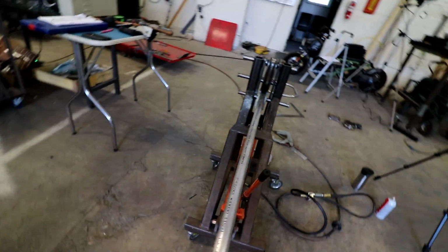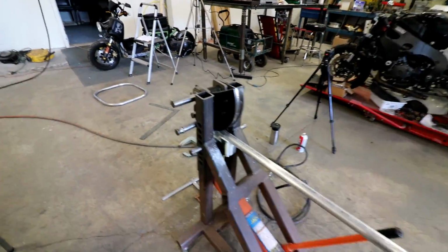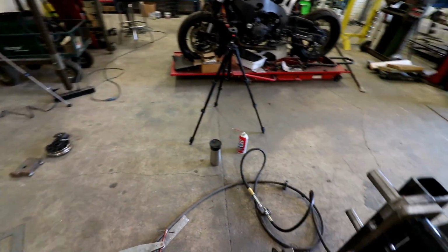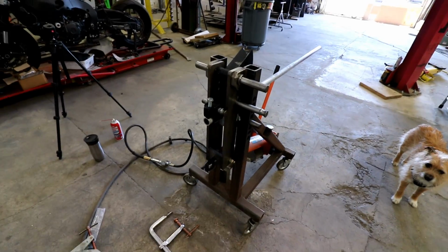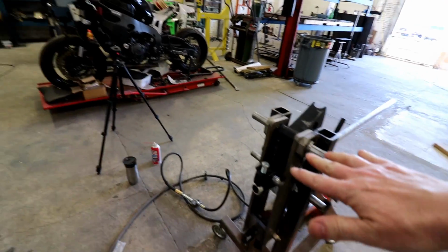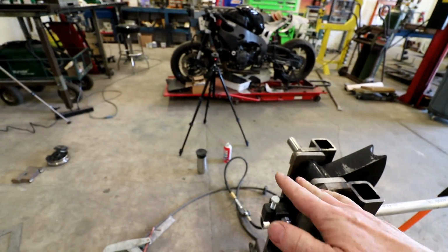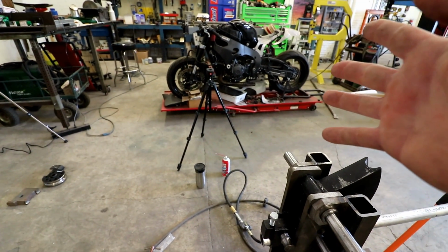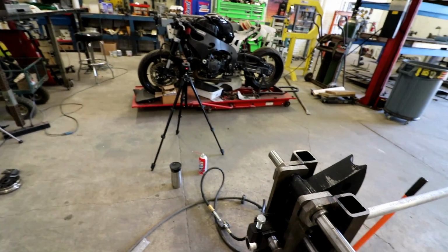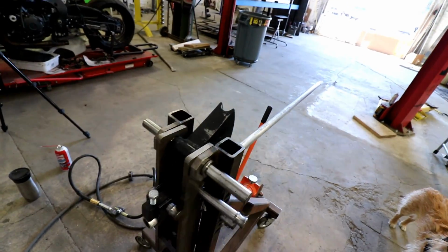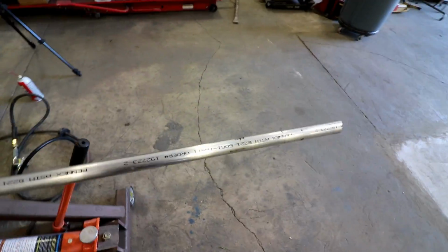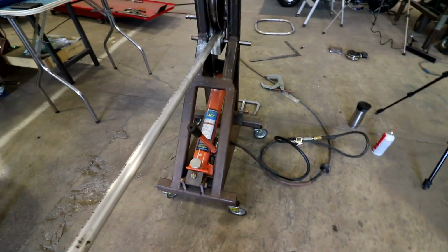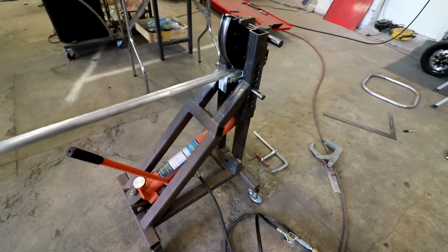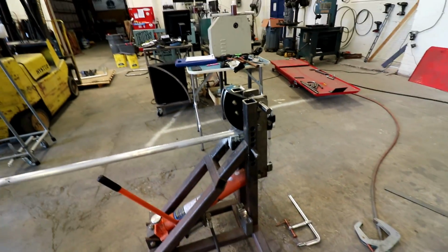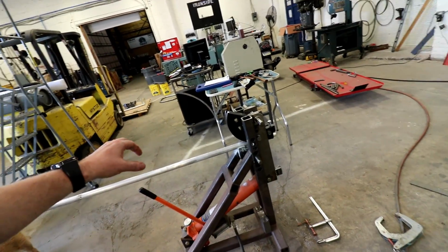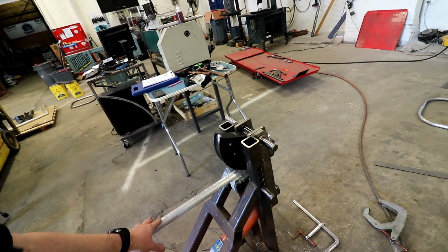And I found that when I heated it with the torch, I had about 5 degrees of spring back. In other words, once it bends, and I'll show you in the bend here, once you let off the pressure, it's going to spring back. So I had about 5 degrees. Now, when I put it in the oven and heated it, I found that I had about 10 degrees of spring back. So I still have some hardening in this material. I didn't get it all the way annealed.